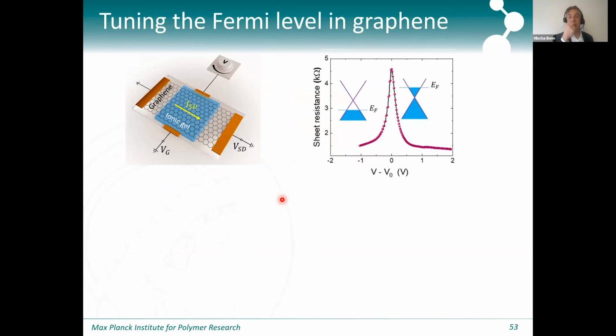Yeah. That is a very good point, and this is also part of the reason why we wanted to use this gated device, because as you can see here, depending on the gate voltage, you can change the resistance, and so the doping. So you can go from P-type to N-type doping. This is the N-type doped branch, this is the P-type doped branch, and you can indeed achieve the same using different substrates, but here you literally have a knob where you can just change the gate voltage, and you can tune the Fermi level. So it's a very good question, and we address that question using such a device here.